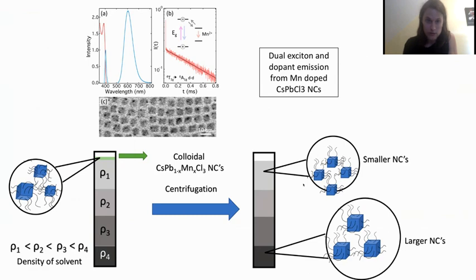So that's interesting with the parents themselves, but we decided to apply the Hobby group's competitive separations technique to these samples. Essentially we take the parent and do this so-called ultra density gradient centrifugation, so you can size separate the nanocrystals. Then we can look at the role of size on the photophysical properties of these dual emitters. Next slide.